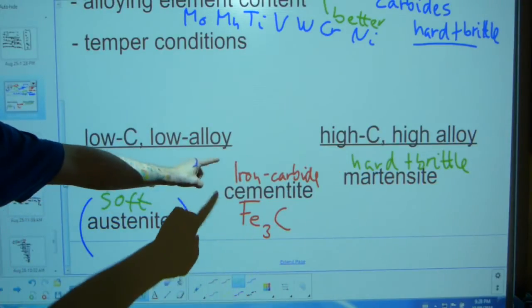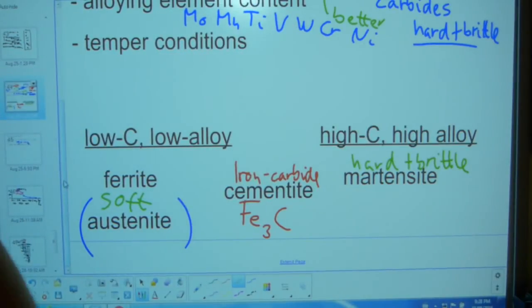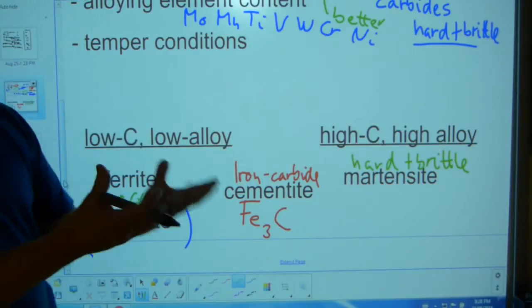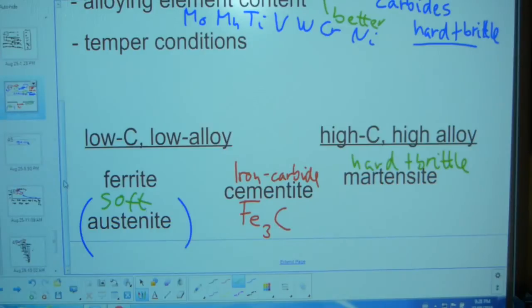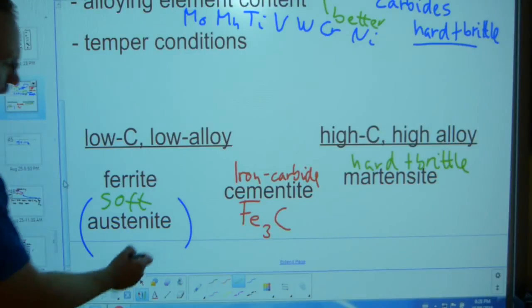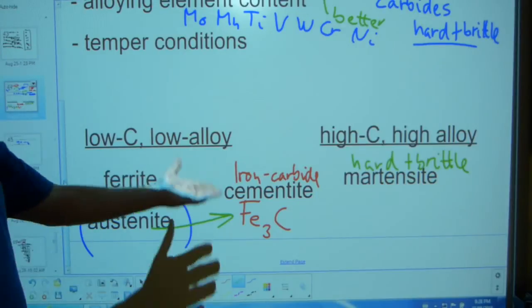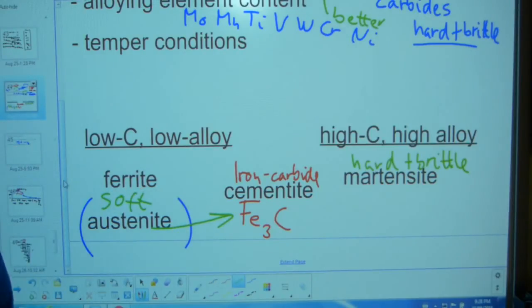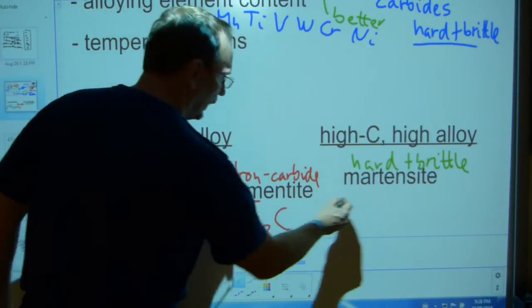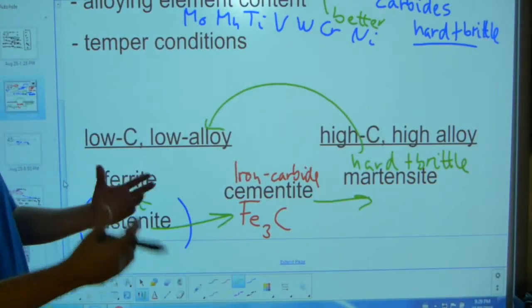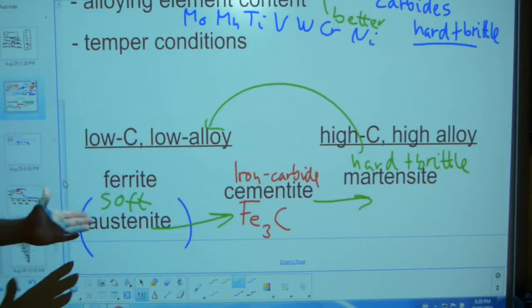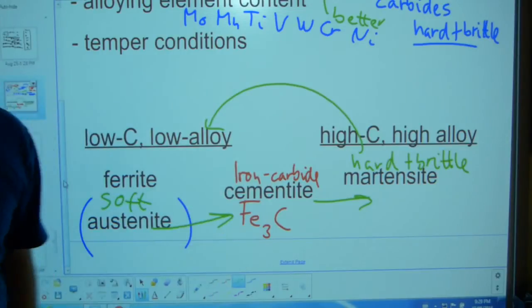All right. What happens with this martensite and with this cementite that's iron carbide, so that's why it relates to the previous story of carbides, is that you have to anneal it or temper it, or some kind of heat treatment has to be done on it to soften them. But here is the austenite's revenge. Austenite is face-centered cubic, and austenite leaks carbon. And as it leaks carbon out, that carbon makes iron carbide compound with the existing iron, and that makes martensite. Even though some of these are being softened and dissolved into ferrite and dissolved carbon, austenite releases a lot more carbon that makes iron carbide than the amount of existing iron carbide is being softened.